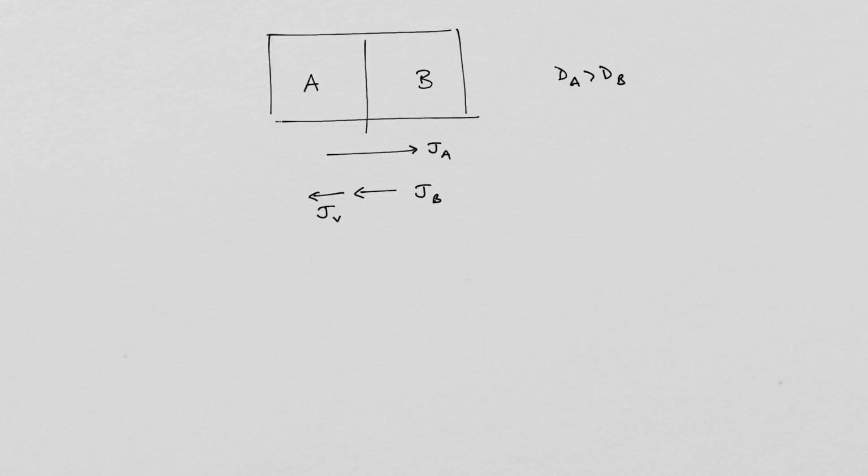That's not realistic. That's not what really happens. It must actually be the case that within real materials there are always sources and sinks of vacancies, places where, although we talked about that vacancy formation energy being of the order of 1 eV per atom, we need some places in these materials where it's much less than that. Okay, so I think that's enough.